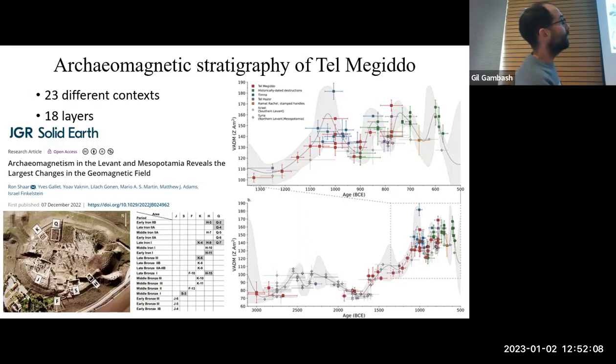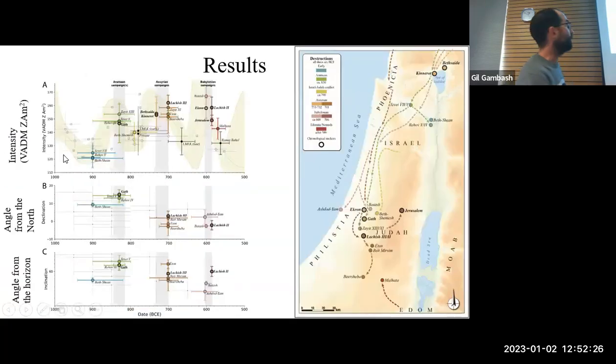So you see the results here, the red results are all the results from Tel Megiddo. And zoom in here on the end of the Late Bronze and the Iron Age, you can see the combination of this with previous data, like the blue that comes from Timna, from copper slag, and the green, which is the destruction layers that I studied. So these are the results from the destruction layers. You can see here the intensity, as I explained before, the different destruction events are marked by different colors. And you can see the changes in the magnetic field. The light green line is the Bayesian model we use, which tries to predict the behavior of the magnetic field according to the different data.